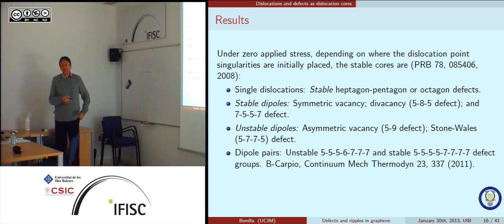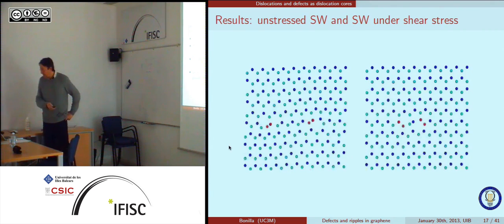So for instance, if you have only one dislocation, you run the thing, and you discover that depending on where the dislocation point is placed, you see two stable defects, which are a pentagon-heptagon pair or an octagon with a dangling defect. Of course, these ones are not observed because the dangling defect gets saturated with something else, and they get kicked. Then stable dipoles, depending again on how far you put the two dislocation points, can give you a symmetric vacancy or a pentagon, octagon, pentagon defect, or this other defect I showed before. Then the Stone-Wales defects are unstable, and then there are more complicated defects that we analyzed because they were observed by the experimentalists.